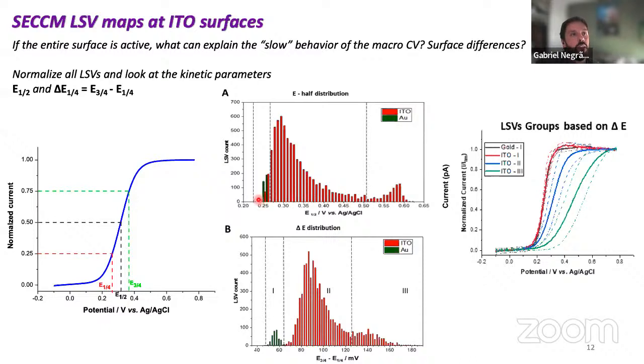It's quite nice to see that it's a very broad distribution. I have some things that have a very small half-wave potential, near to what we expected to have, for instance, for gold, and these were comparing for gold. So we have places which have a very high half-wave potential, but we also have places that have a very low half-wave potential, right? So they're very far away from the expected.